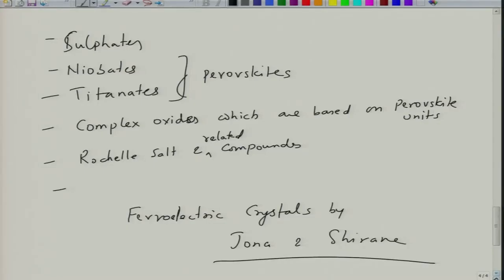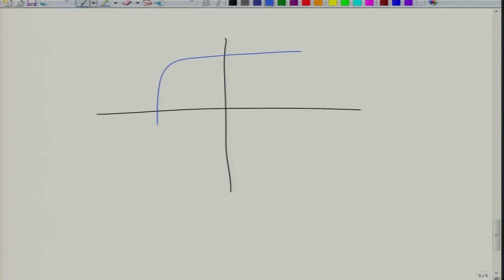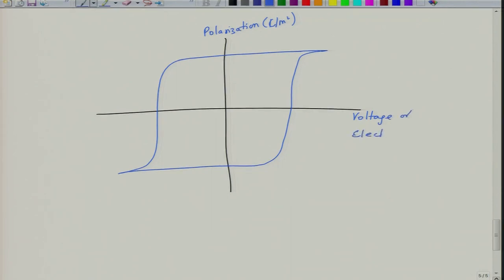Now we'll see what a ferroelectric material is. A ferroelectric material by nature is a nonlinear dielectric. When you switch a ferroelectric under electric field, it shows a hysteresis curve like this. Just like a ferromagnetic material, the ferroelectric material also exhibits what we call hysteresis. So this is polarization, which is typically in coulomb per meter square, and then voltage or electric field. So this could be in volt, or volt per centimeter or volt per meter. What it shows is a hysteresis loop.